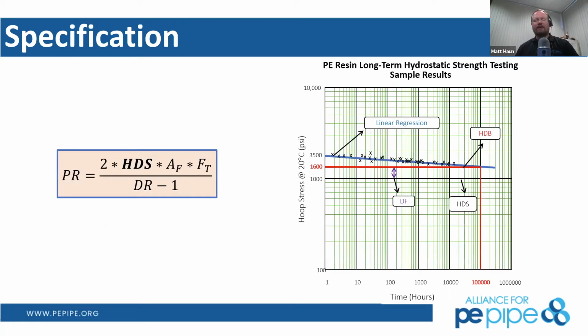So in TR3, hydrostatic testing is performed on a whole bunch of pipe samples that are going to be conditioned to temperatures higher than normal operating conditions for over 10,000 hours in an array of incremental stress levels, those stress levels being way higher than what you would ever expect in a real pressurized situation. And so on this chart, you'll see each of the X's, they kind of indicate a ductile failure point.